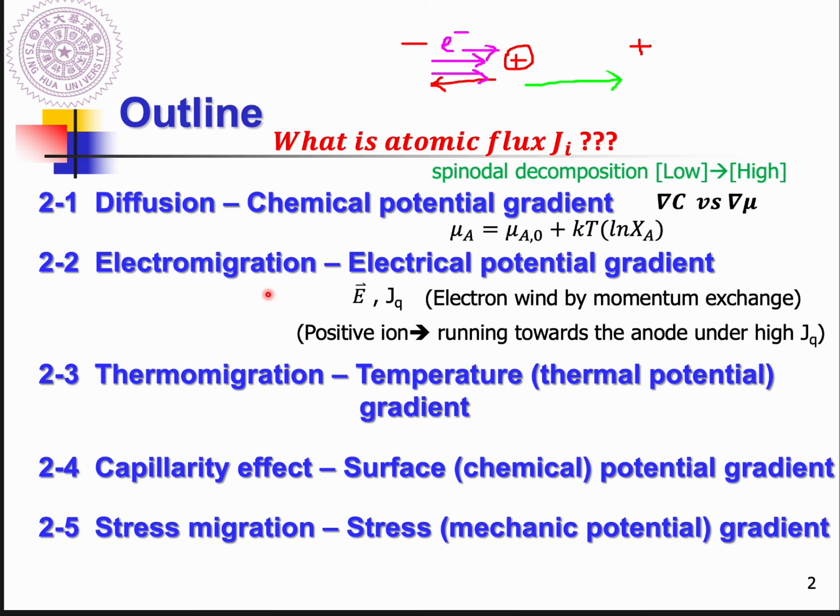Okay, and as you know, in the semiconductor industry, the line width actually decreases dramatically. That will make the current density increase dramatically, right? So electromigration will always happen, and easily, under high current density. So this phenomenon, we need to know what it is, and we can design and do something to avoid this effect, to increase the reliability of our device.